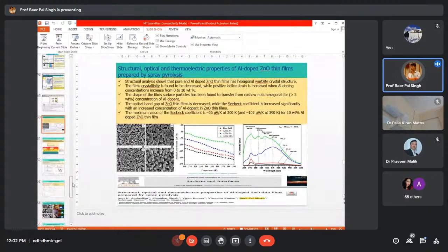This is about the different applications of zinc oxide. One of my students deposited aluminium doped zinc oxide thin films using a very simple spray pyrolysis technique, and again he got very wonderful structures, cashew nut-like structures seen by scanning electron microscope. He went for thermoelectric measurements of this aluminium doped zinc oxide thin film, calculated the Seebeck coefficient and more, and claimed that this material may be very useful for thermoelectric applications.